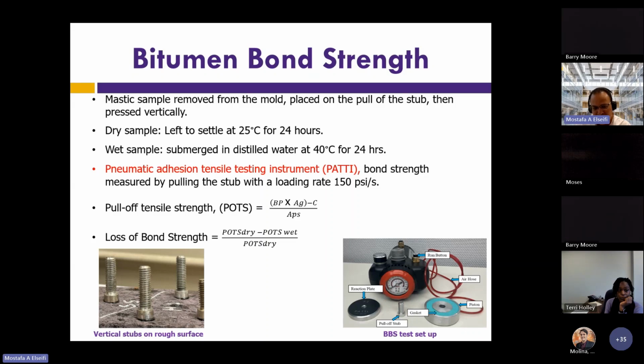And then you pull it at a loading rate of 150 psi per second. And you measure the pull-off tensile strength. So this test is done under dry condition and after wet conditioning. The wet conditioning consists of submerging the specimen in distilled water at 40 degrees C for 24 hours. So we measure the loss of bond between the dry and the wet. And again, it gives us an assessment of the strength between the mastic and the aggregate. And again, it's a very important property that relates to the adhesion strength that is achieved in the mix.